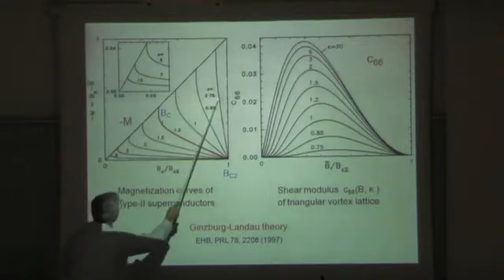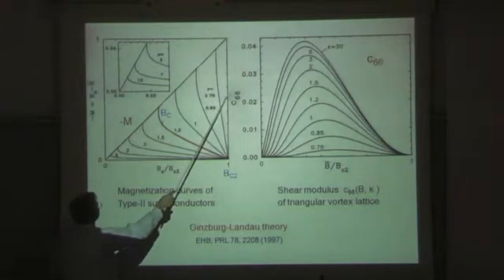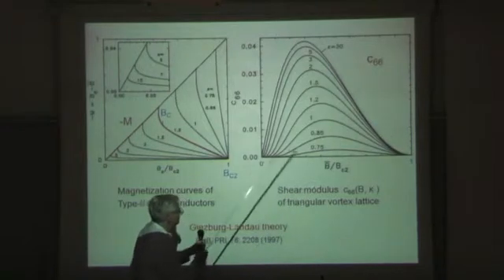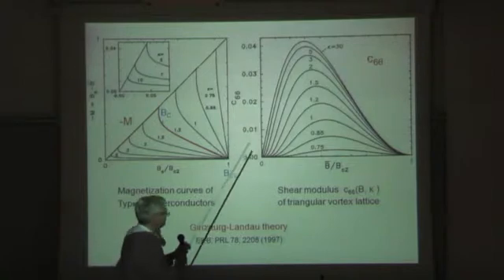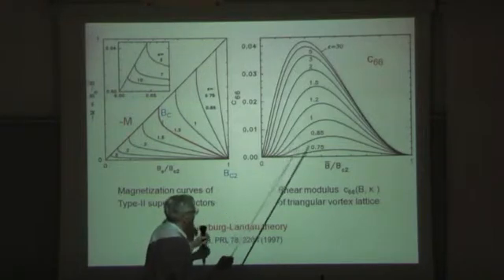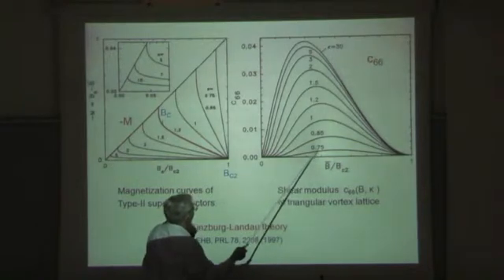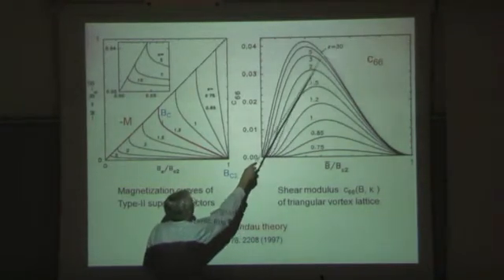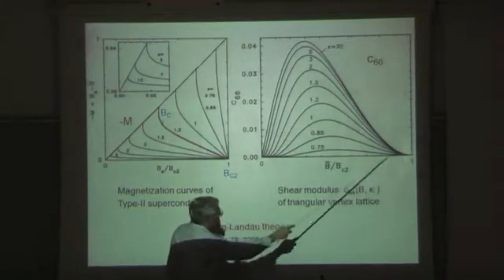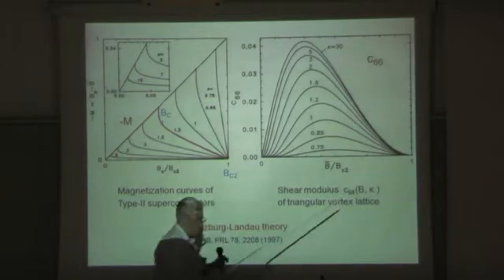I calculated magnetization curves for all inductions, for all applied fields, and for all kappa parameters — from one over the square root of two up to very large values. I also calculated the shear modulus. The shear stiffness of the vortex lattice is very important because it enters the summation of random pinning forces, which determines the critical current density. When kappa is one over the square root of two, the shear modulus is exactly zero. When kappa increases, the shear modulus goes to a saturation value reached when kappa is greater than or equal to 30. It also vanishes at zero induction and at Bc2.